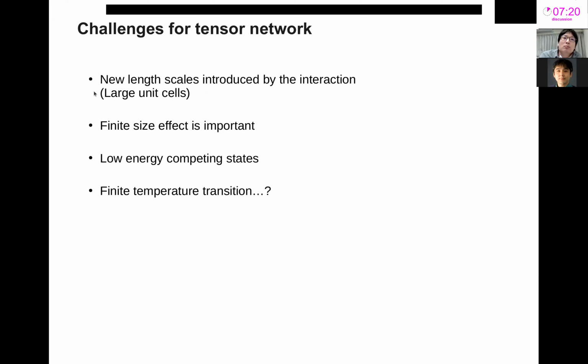So why is this so difficult? The first thing is that you see this new length scale, which is the stripe wavelength introduced by the interaction. Although all the interactions are only on-site, and the hopping is just nearest neighbor and next nearest neighbor, you have this new stripe wavelength introduced by the interaction, and this makes it difficult to know how large a unit cell you need to consider, and it's also very sensitive to the finite size. So the finite size effect is important, and also there are many low energy states, so you need good accuracy to be able to distinguish these states.